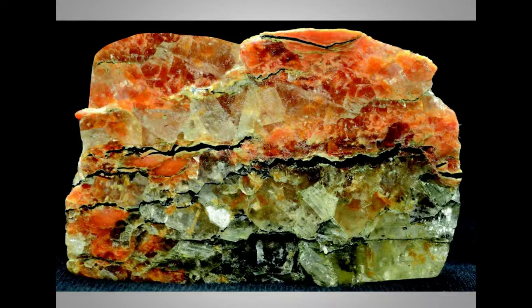This is a color close-up from that same project that shows how the grout represented by the dark lines here in this salt particle effectively filled the cracks as small as 6 microns. This grout was actually designed by the Department of Energy through their Sandia National Laboratory Facility, and their purpose was to effectively seal these microfractures in order to contain the nuclear waste within these giant salt caverns that were located about a mile beneath the surface of the ground.